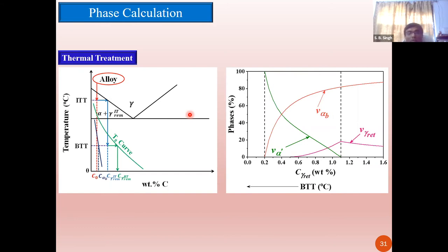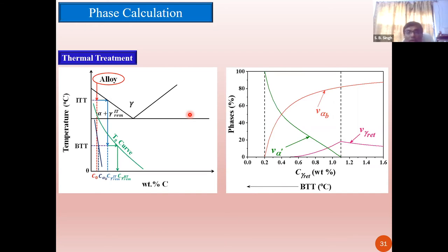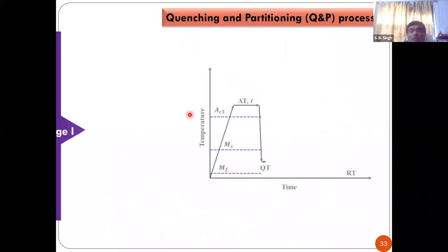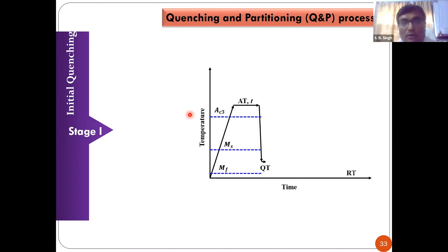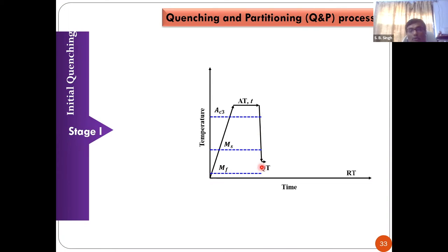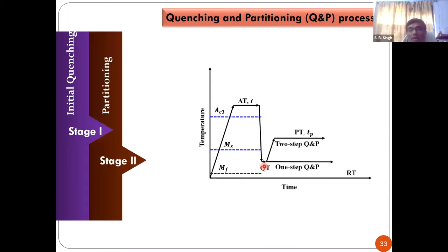If bainitic ferrite indeed contains about 0.28% carbon as our results show, then it would cause strengthening of ferrite. We used this knowledge for designing quenching and partitioning (Q&P) treatment. This is a simple heat treatment proposed in the early 2000s by Speer and co-workers: after austenitization, the steel is quenched to a quenching temperature where it partially transforms to martensite, then given a one- or two-step partitioning treatment where excess carbon of martensite is released into austenite, enriching it. In TRIP steels, carbon enrichment of austenite comes from ferrite transformation in the intercritical region and during bainite transformation, whereas in the Q&P process, it comes from decarburization of martensite formed during initial quenching.